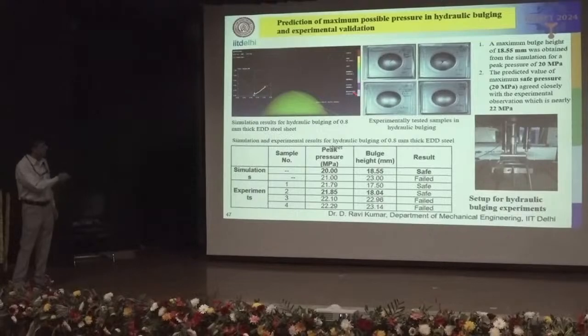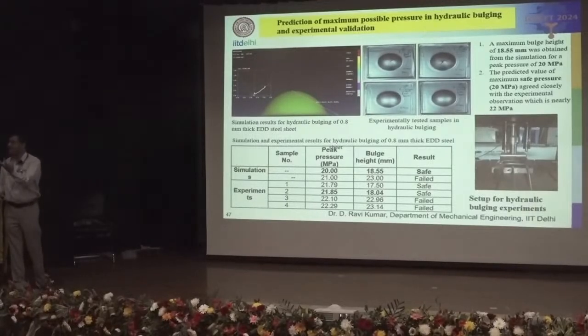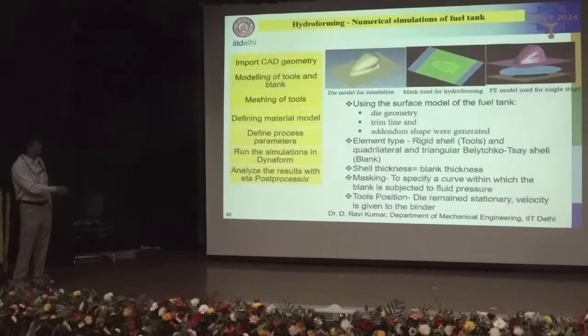And we have found out initially from simulations as well as lab-scale experiments what is the maximum pressure up to which this sheet can be formed by hydroforming. We have found that it can go up to nearly 20 to 21 MPa, that is 200 to 210 bar. Okay. So after experimental validation of this, we carried out the hydroforming simulations.